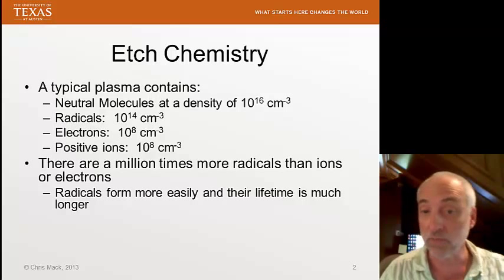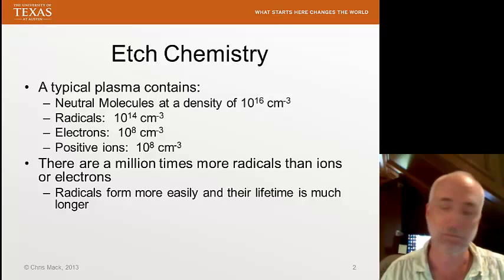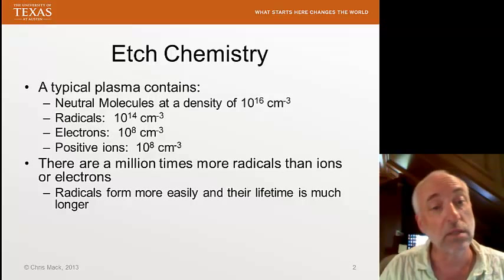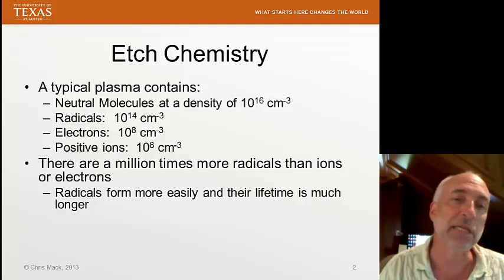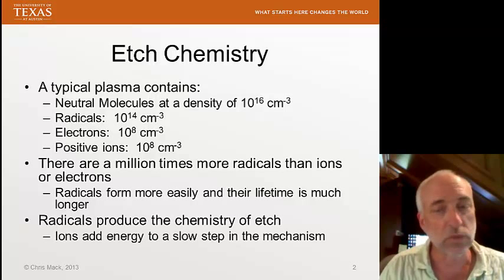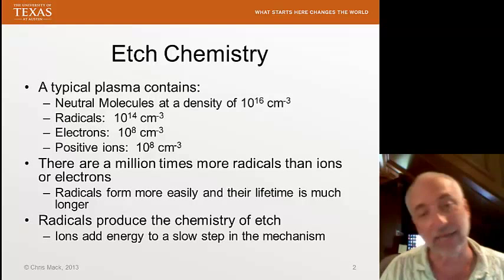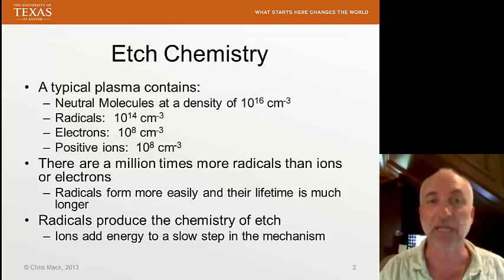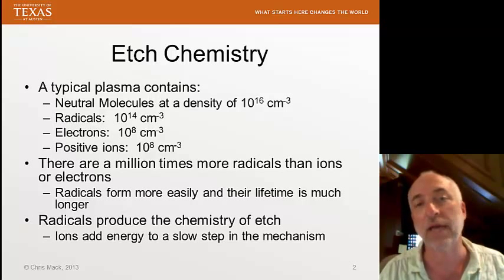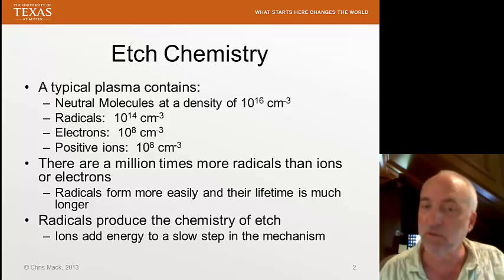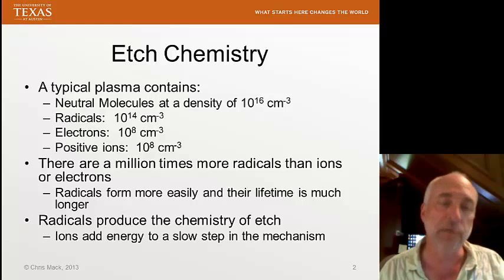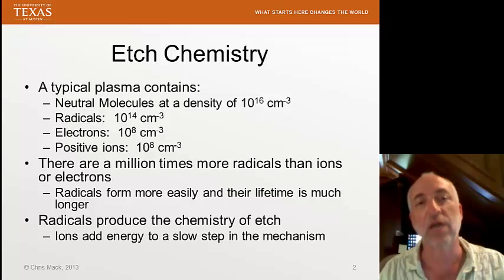The radicals form more easily and have a much longer lifetime. Ions don't have a long lifetime — they disappear quickly, either because they're accelerated out of the plasma, or they find another electron and recombine. The free radicals last a long time until they react chemically. So there are a lot more free radicals, and that's why they tend to dominate the etch chemistry. It's the radicals that produce the chemistry, and then ions add energy — speeding up some slow step in the mechanism to enable reactive ion etching to work.